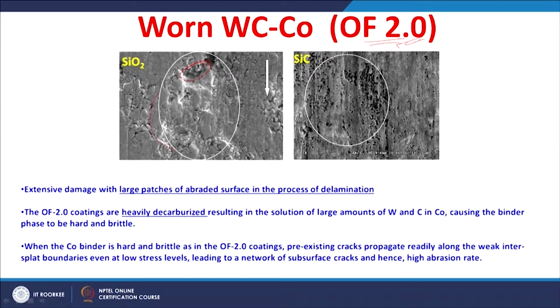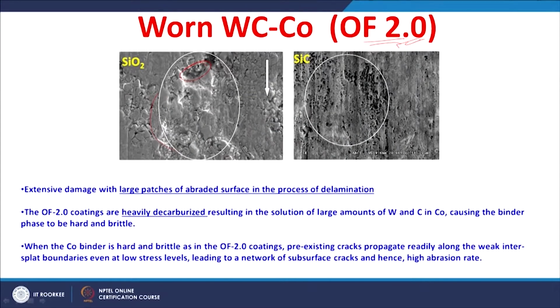So, once this is dissolved, that leads to the binder phase becoming harder and brittle. Once the binder phase becomes harder and brittle, you have cracks propagating easily along these weak intersplat boundaries. Such propagation is possible even at lower stress levels. So, there is easy propagation of these pre-existing cracks, and that results in a network of cracks, and hence you get a large amount of material removal.